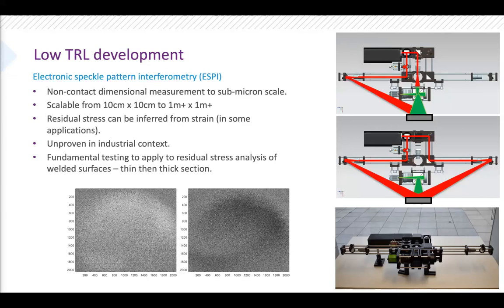So we took this core concept and we were looking at scaling it up to something that can be effective at scale on components that are relevant to the nuclear industry. Because there wasn't really anything on the market that was capable of testing the methodologies that we wanted to do, this work package was about developing a prototype transportable ESPI unit that can do both in-plane and out-of-plane electronic shearography, essentially, to evaluate whether it would be capable to measure this strain. Whether that could then be correlated to residual stress on a large component in process is multiple years of further development, but we were just establishing whether the sensors are going to be capable of at least capturing that information. And even if you couldn't tie it to residual stress, measuring macroscopic strain in terms of deflection would be useful as an established in-process methodology.